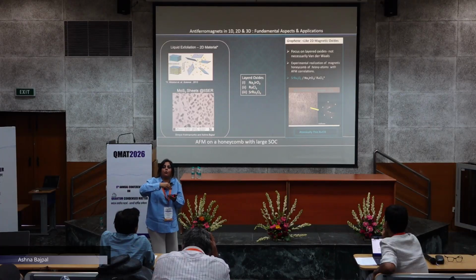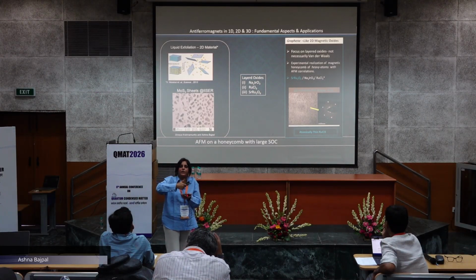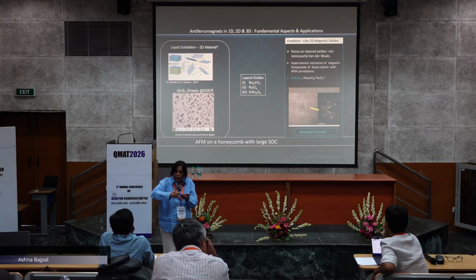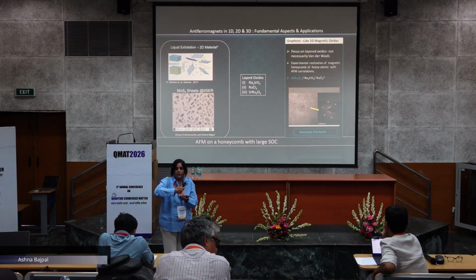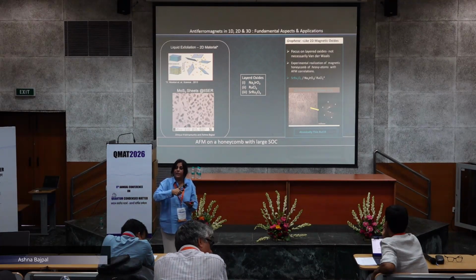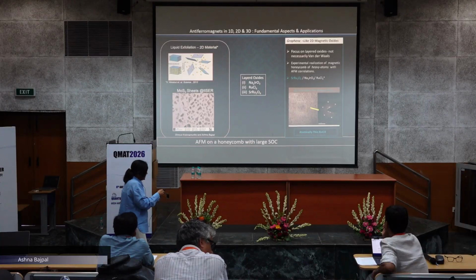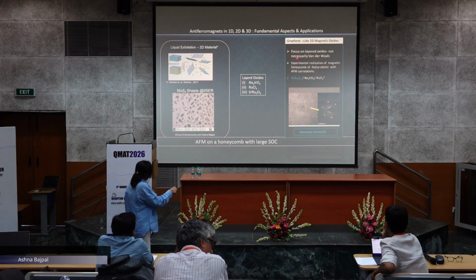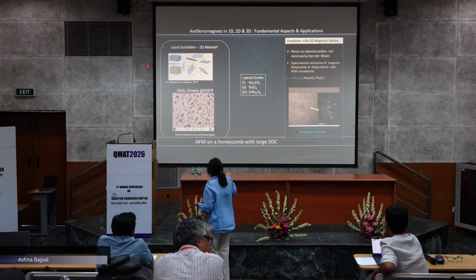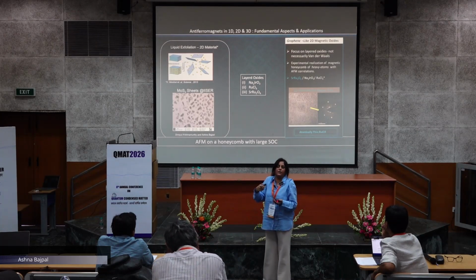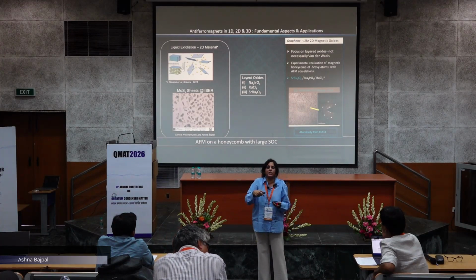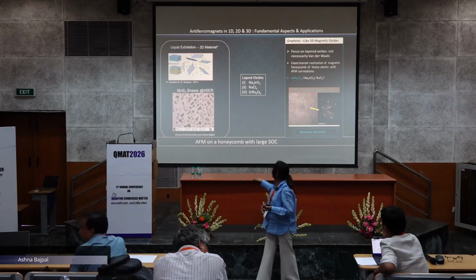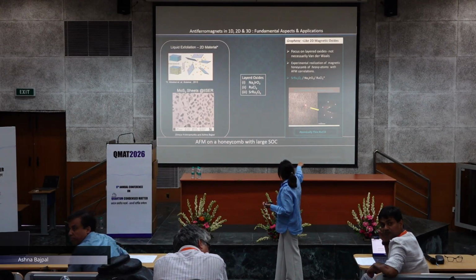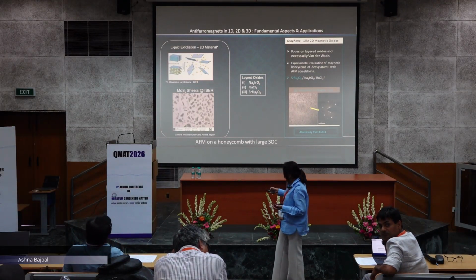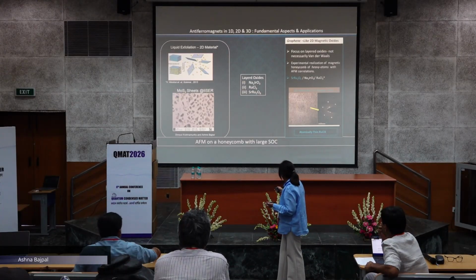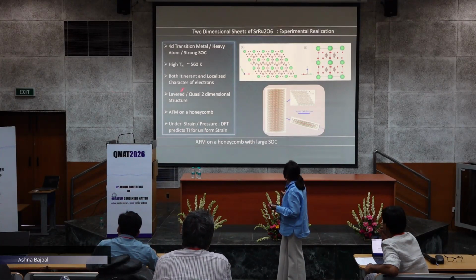SrRu2O6 is indeed quasi two dimensional, because even though it is not van der Waals, the out-of-plane interactions along the C axis are weak. It is very easy to exfoliate, as you will see. RuCl3 was easiest. We use a method called liquid exfoliation, which is basically a series of centrifugation and sonication, which enables you to get the 2D sheets. This is what you are seeing for RuCl3, which is Yogesh's crystal, but today our focus is on SrRu2O6.